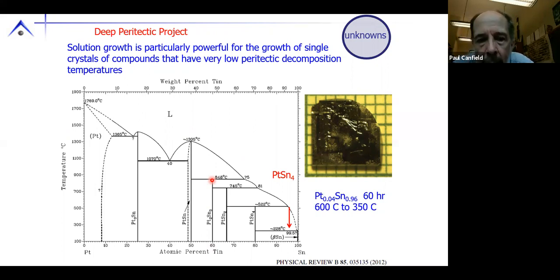It becomes platinum tin and this liquid. And as I heat up more, I have platinum tin, but more and more of this liquid of a changing composition, okay? Only when I get to this temperature, above this, do I have a homogeneous liquid that is 2 platinum and 3 tin. And as I keep warming up, I have that, okay? Now, the implications of this are more profound when you cool down.